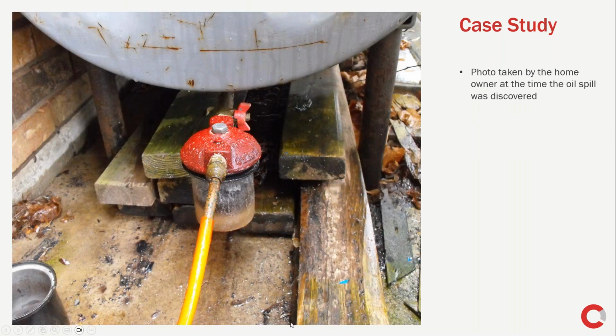Right, so in oil installations, water can accumulate due to condensation, and we know that water is heavier than oil, so it makes its way to the bottom of the tank. And once the oil is set to run out of the tank towards the furnace, because the water is at the bottom, water will run out first and then accumulate in the filter. So the homeowner should have checked for stagnant water, but apparently hadn't done this for at least 2 years.